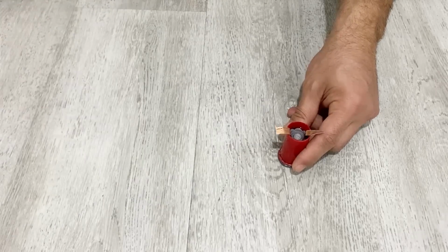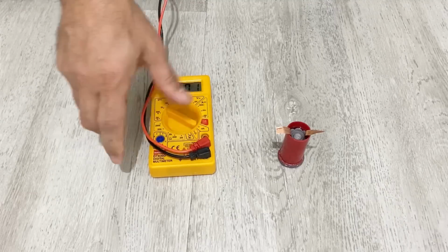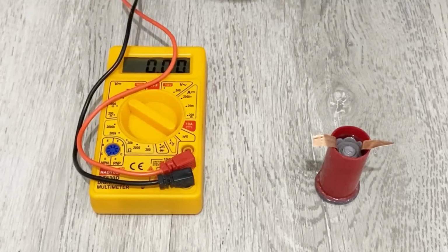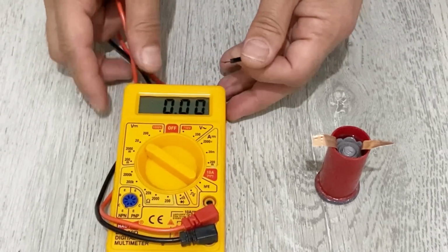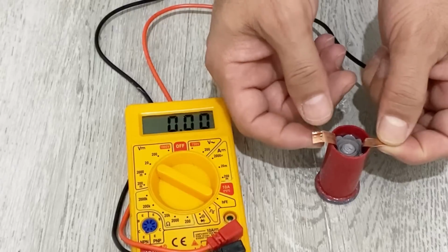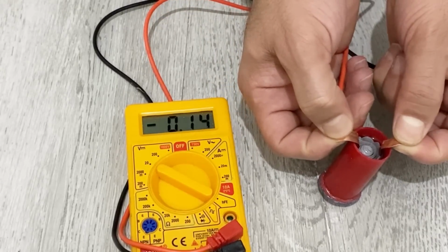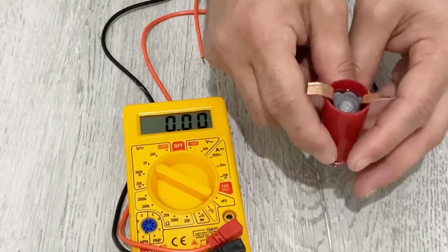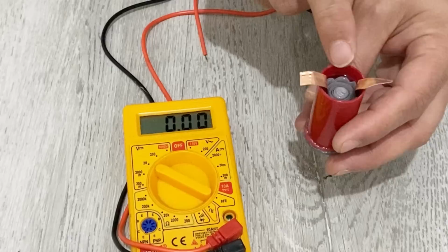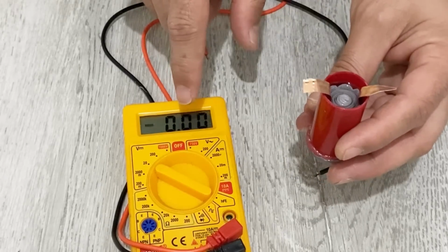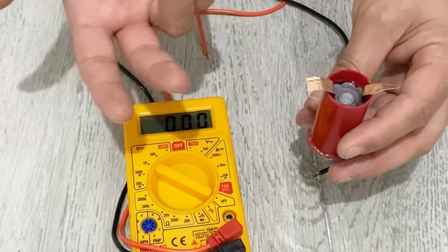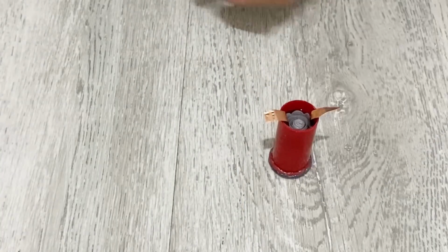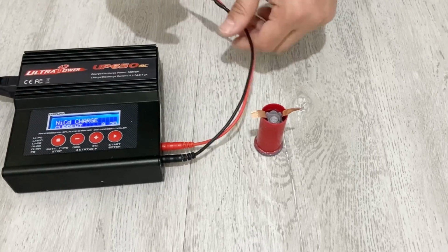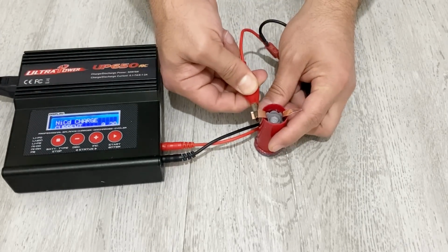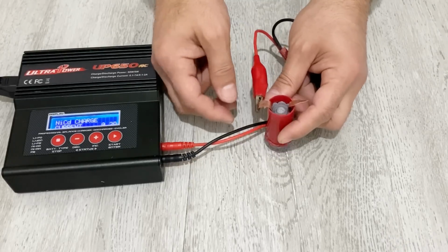Before charging the battery, my friend, let me show you the initial voltage of our battery before charging it, because I need to show you something. Before charging the battery, the voltage is about 0.14 volt, because of the distinction of the materials we used on the positive electrode and on the negative electrode, so it's very normal. It indicates that this is a real battery. Now we will charge our battery, my friends. I will charge my battery for about 1 hour, and after that we will test it.